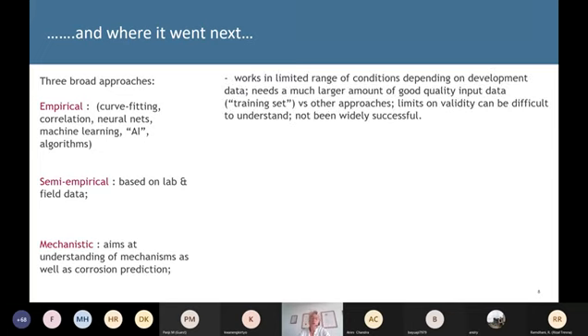We thought a lot about it, but what was apparent was that when you build up a knowledge base that these systems can work in, you have to have a set of data. You need an awfully large amount of good quality input data. Normally you need a training set of data that you use to set things up, to build your artificial intelligence and write your algorithm, and then you test it against other things. It's very difficult to give that system validity beyond where it started, just as with the original nomogram, to be fair. But I can say that at the moment, success has not been great with CO2 corrosion. There could be other areas where this does have success, and we now have much better computing power, so there could be opportunities in the future, and we can come back to that at the end.